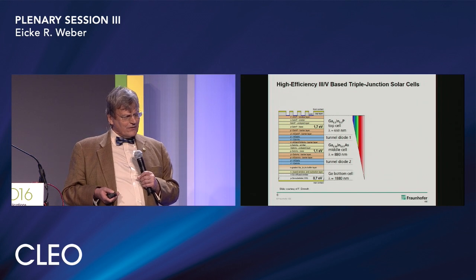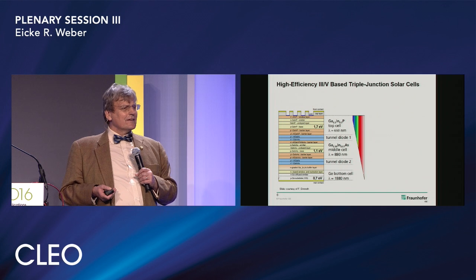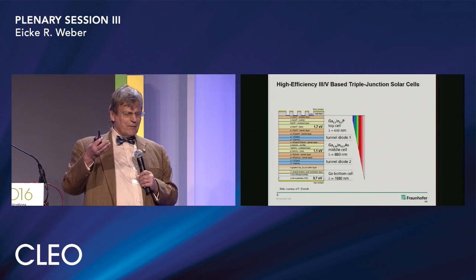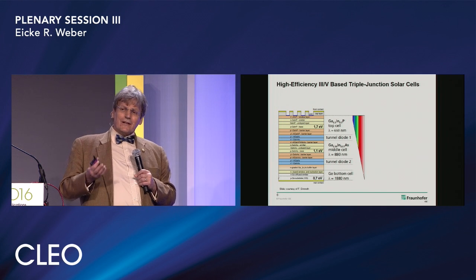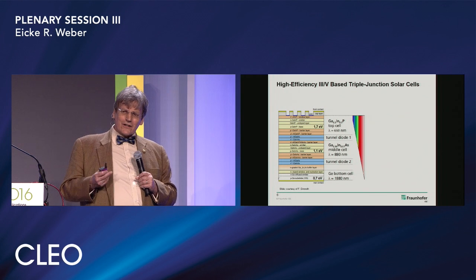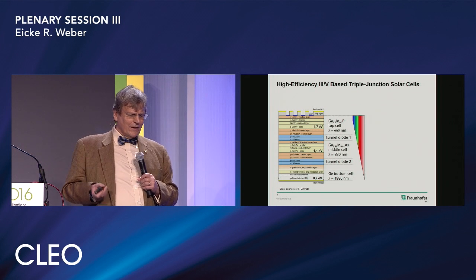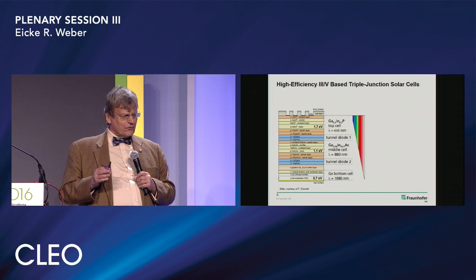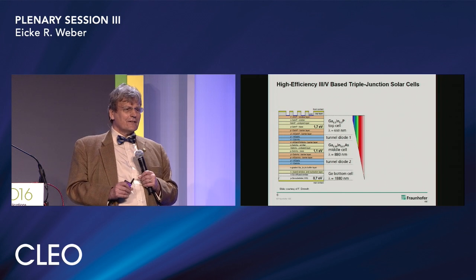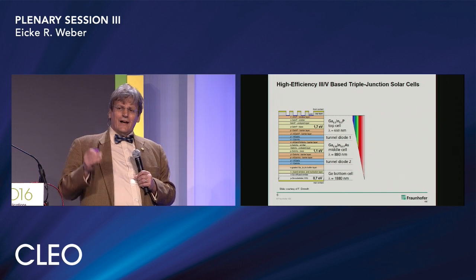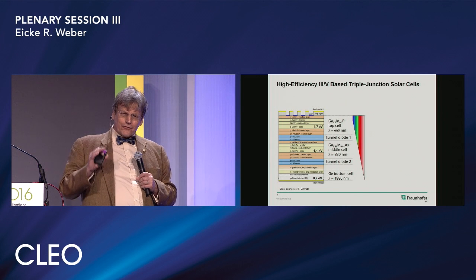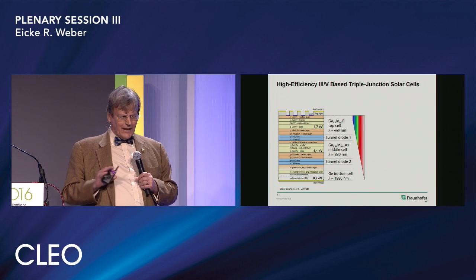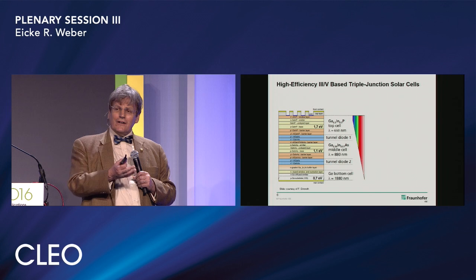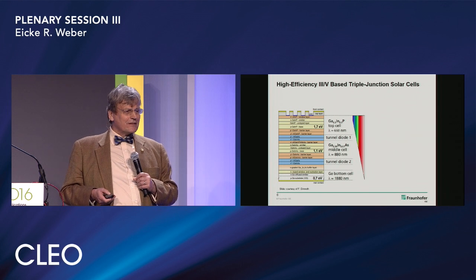The structure, as you see, not only needs the three materials with p-type and n-type conductivity, but in between you need as well tunnel junctions to bring the carriers from one material to the next. And of course, at each of these layers, at each of these interfaces, utmost care for defect-free structures is absolutely essential. And therefore, making such structures is very expensive.